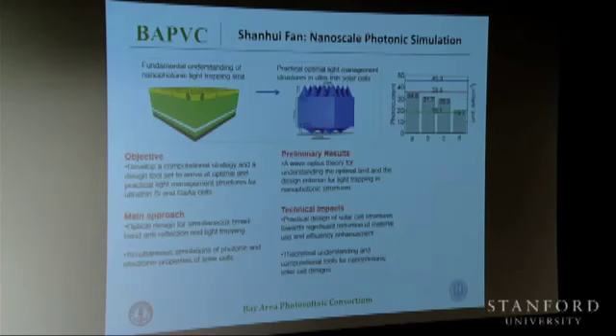The backside of the cone is where the light coming in hits the backside of the cone and gets scattered. So you want to couple the light to travel horizontally. Shanhui Fan's simulation showing using 2 micron thick film. This is a number you get out. In the case of A, this is about 35 milliamp per centimeter square of current you can generate.